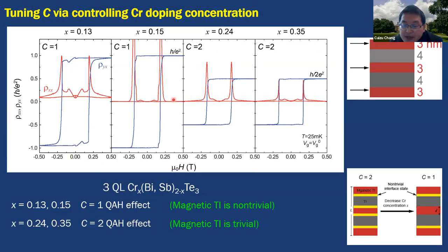And in the same sample configuration, we found that the Chern number in this kind of multilayer sample can be tuned by controlling the chromium doping levels. For example, take this sandwich layer as an example. This is the magnetic TI layer and this is the undoped TI layer. If we change the magnetic doping level in the magnetic TI layer, we can see that with a lower doping level, the sample shows the C equals 1 quantum anomalous Hall effect, and with a higher doping level, it shows the C equals 2 quantum anomalous Hall insulator.